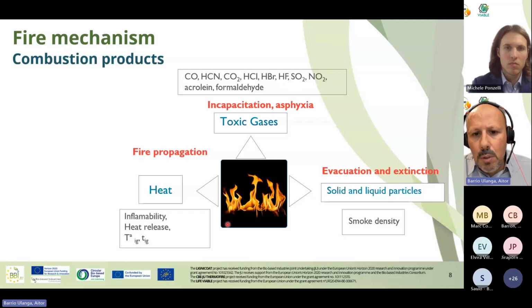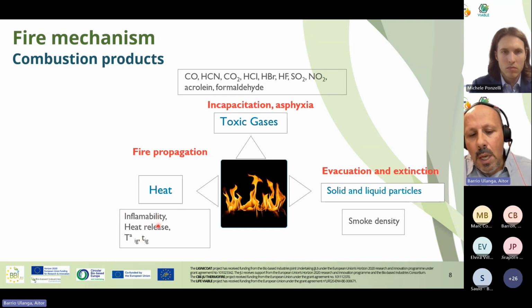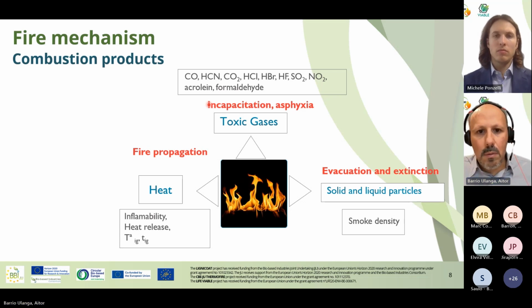In case of fire, in case of combustion, you have different outputs. You have heat. When there is fire propagation, you have a lot of nomenclature: the inflammability, heat release, temperature of ignition, time to ignition. But you also have smoke, so dark that you cannot evacuate, and in some cases it is worse than the exposure to fire. So this is a smoke density parameter. But you have, for example, in railway or in other standards in vehicles, to declare the toxicity, because these species can promote incapacitation. So these three phenomena are very important.